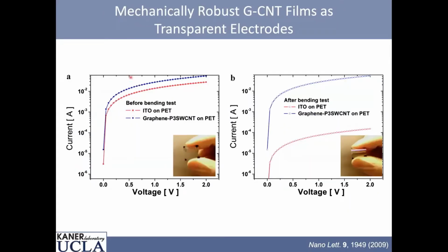Why? Because my colleague's interested in solar cells. And so right now for solar cells and other electronics, your cell phone and so on, indium tin oxide or some derivative of it is used as the transparent conducting electrode. But we're interested in flexible electronics. And so ITO, you really can't bend it. So we took ITO and we put it on plastic. And then we put our graphene carbon nanotube thing on plastic. Polyethylene terephthalate is the stuff from soda bottles or drinking water.